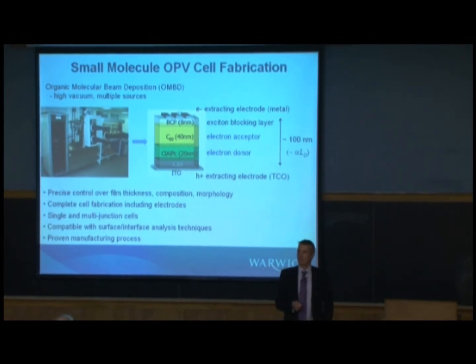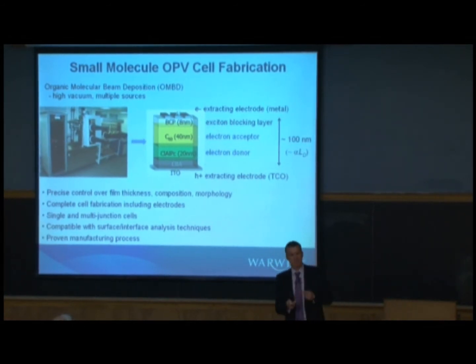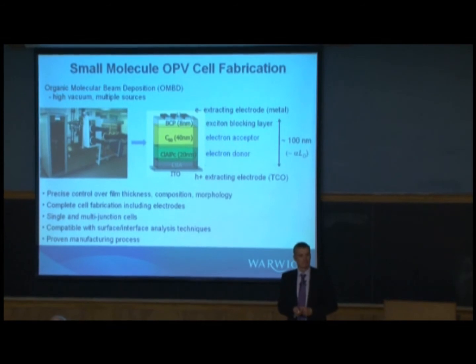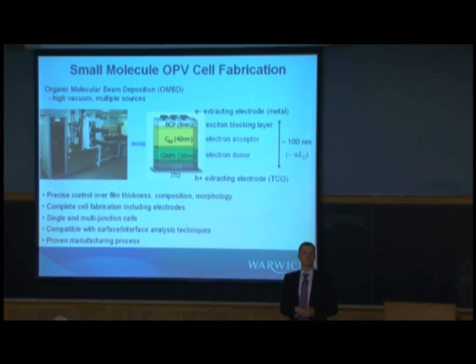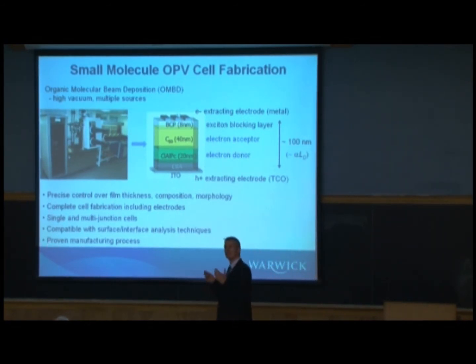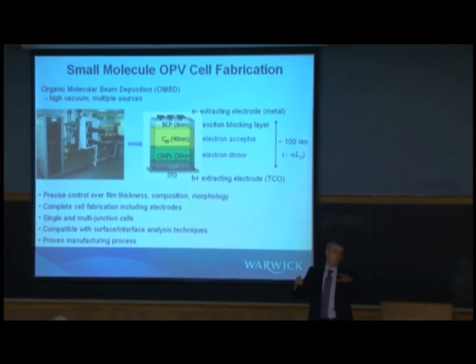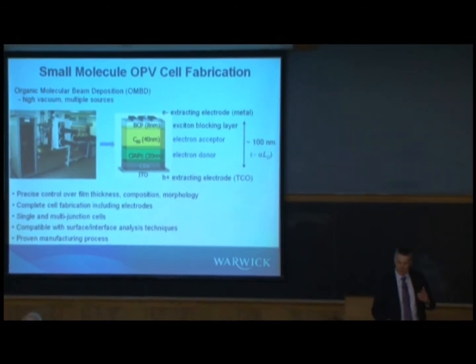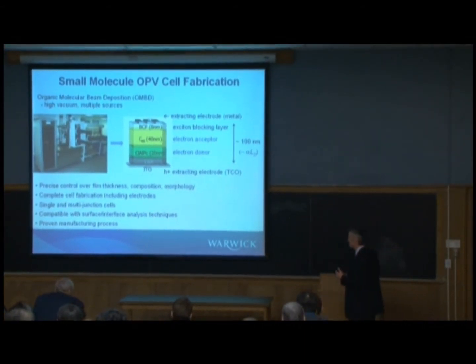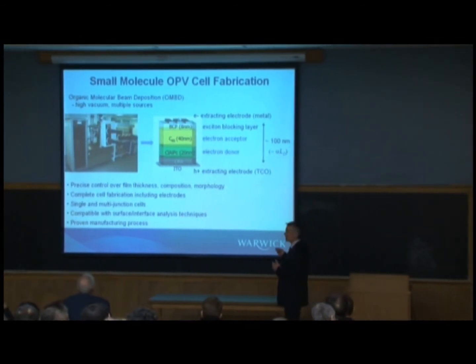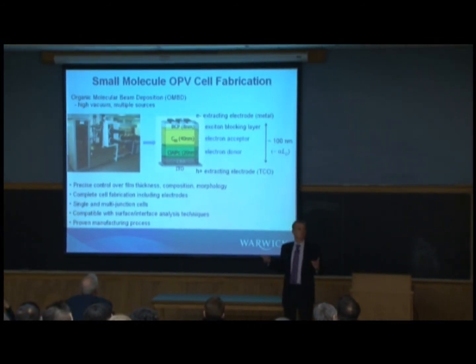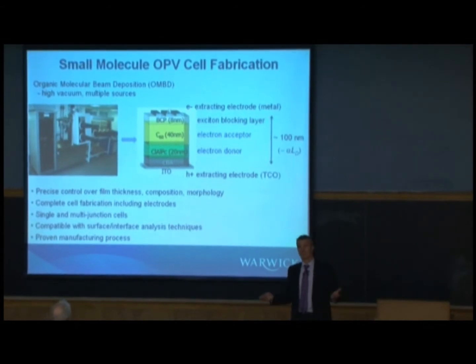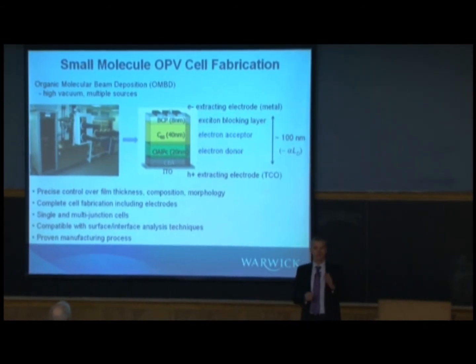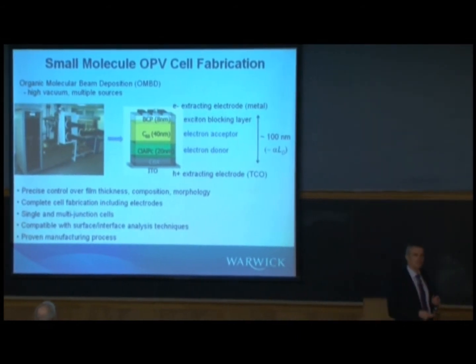If you take a crisp packet and look at the inside, it's got a metallic coating. That coating is put down in a vacuum system. How much is that bag of crisps? It's actually a very, very well-proven manufacturing process. And what the polymer people, and I've probably got polymer people who are going to attack me afterwards, what the polymer people will say, but forget to tell you, is you've still got to put down all the other bits of the device. You've still got to deposit the metal electrodes, and you need a vacuum system to do that. So in fact, vacuum evaporation isn't necessarily an expensive route.